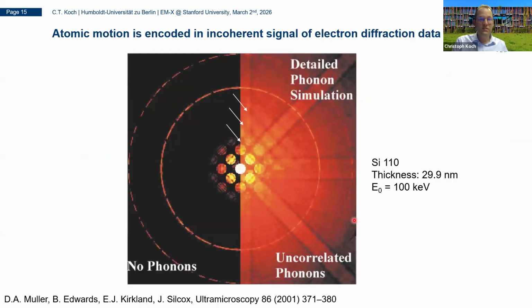And why do we expect this to actually be visible? Well, there's this paper from 25 years ago by Dave Muller in the group of John Spence at the time, where he showed that if you simulate the thermal diffuse scattering using the Einstein model, you get these Kikuchi bands, which many of us have seen before, but there is no structure in these Kikuchi bands. But if you work with the detailed phonon model, which he was able to use because he knew the force constants between the atoms and was able to build the dynamical matrix of silicon and then produce these displacements, you see that the thermal diffuse background looks different. It has these bands in here, which don't appear in the Einstein model simulation.